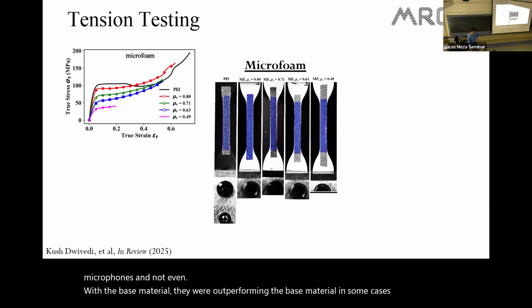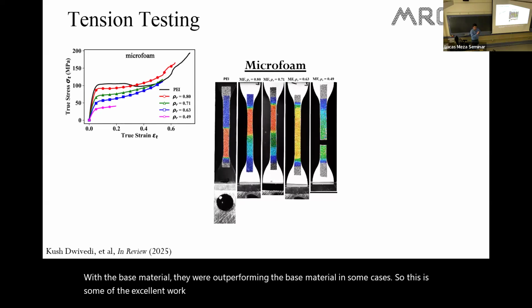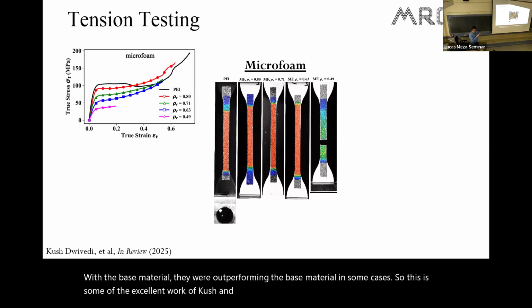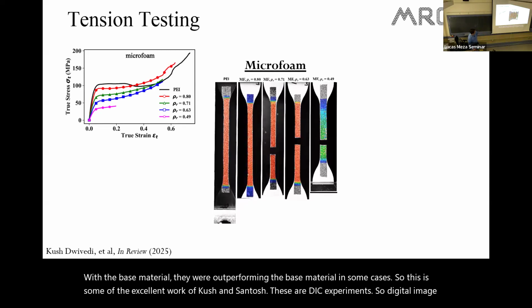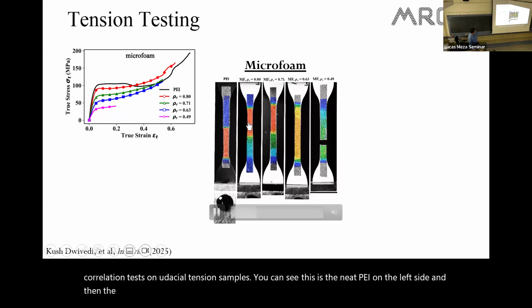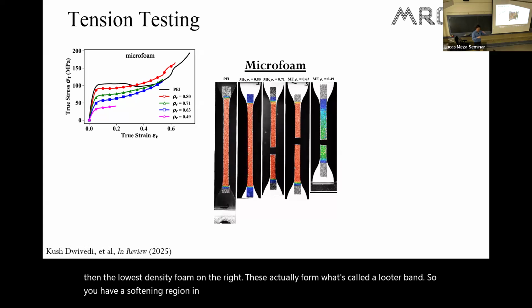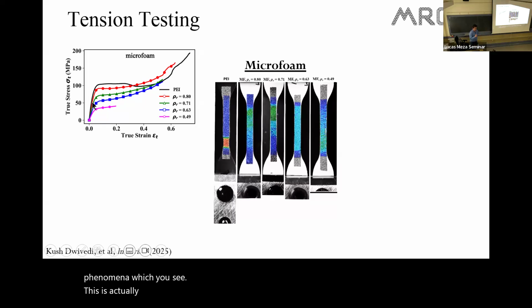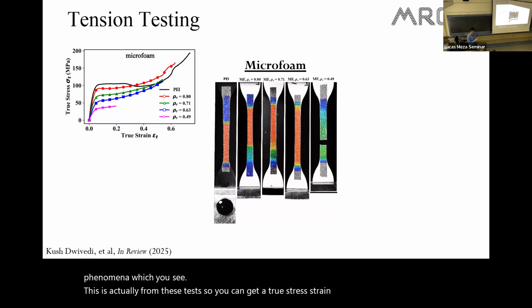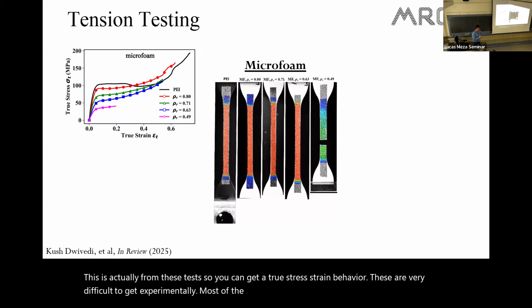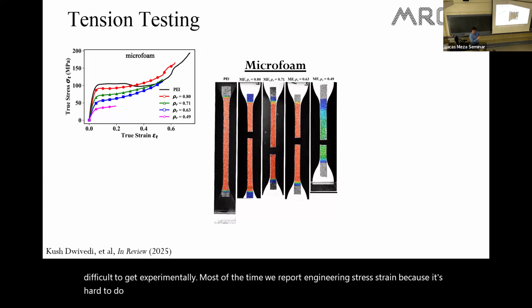So this is some of the excellent work of Kush and Santosh. These are DIC experiments, so digital image correlation tests on uniaxial tension samples. You can see this is the neat PEI on the left side, and then the lowest density foam on the right. These actually form what's called a Lüders band. So you have a softening region in the PEI that propagates through the solid. Interesting phenomena. But from these tests, you can get a true stress strain behavior. These are very difficult to get experimentally. Most of the time we report engineering stress strain because it's hard to do these. But yeah, these we were able to get true stress strain.